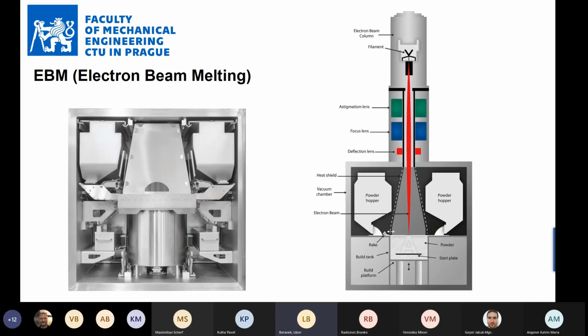And the third aspect over the laser, when you compare those technologies together, is that in electron beam you usually have much bigger power. So these printers are using like 6 kilowatt sources. So you can have multiple focal spots at once. So you have multiple beams basically that are sintering the material at the same time. On the laser machines, you have typically lasers of 500 watts or 1 kilowatt. And the high tech is that you use 1 or 2 lasers. But yet again, the EBM technology is usually much more productive.